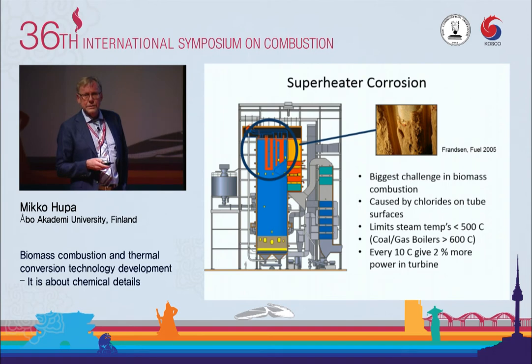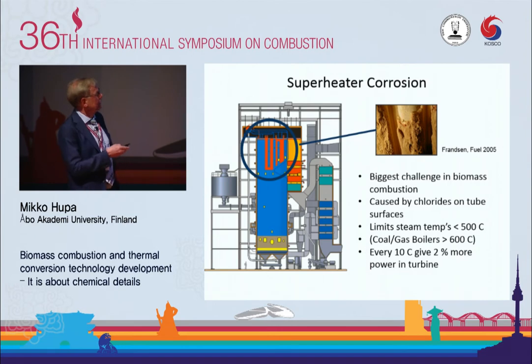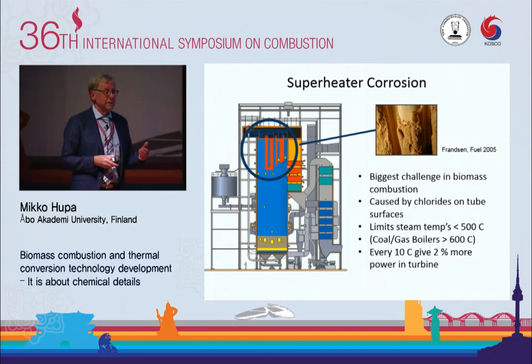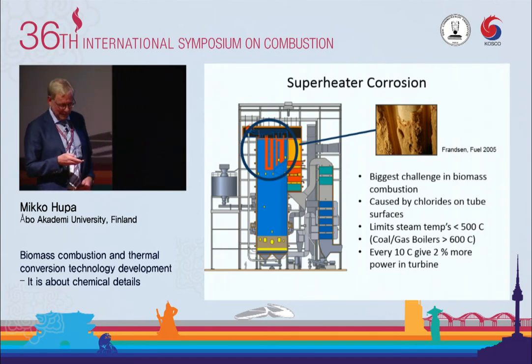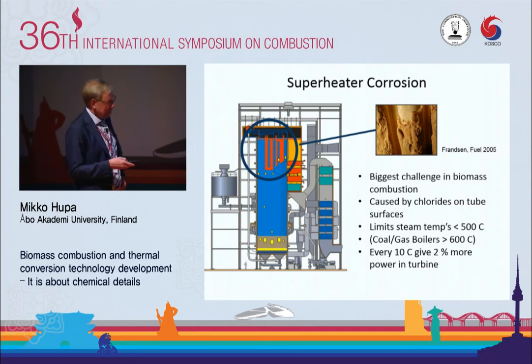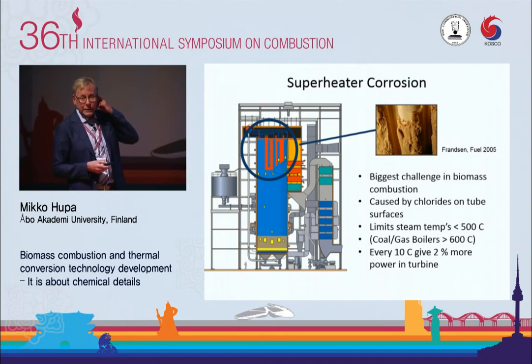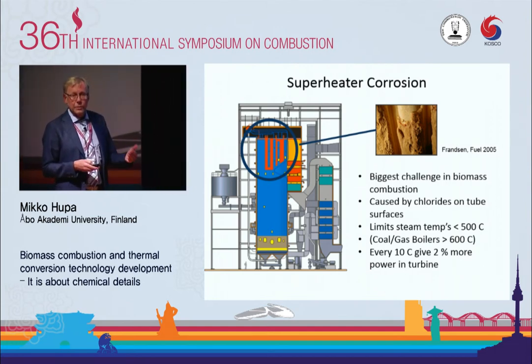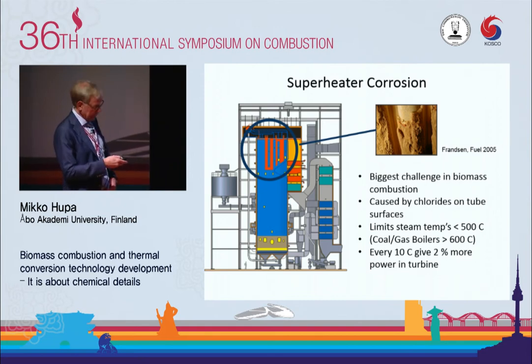500, 520 degrees is a very high number if we burn biomass fuels, while, as you know, in coal boilers, we can go beyond 600, and the materials issue is still not there. And a simple rule of thumb is that every 10 degrees we dare to heat superheater steam higher gives 2% more power in the turbine. You can check if that is a correct rule of thumb, but in that range, which means that there is a big interest in improving this situation. And our boiler manufacturing colleagues, with whom we work together, are extremely concerned about finding solutions to improve the efficiency, the power production efficiency.